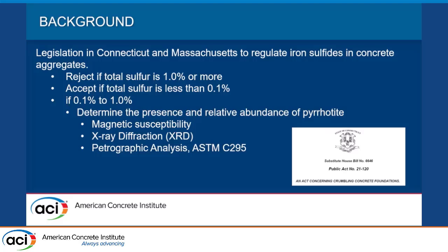So X-ray diffraction is a great tool. It's a wonderful tool to identify the crystalline components in anything, and in this case in concrete or aggregates. The issue with that is that the detection limit is generally identified as 1 to 5%. And again, we're looking at concentrations down to 0.1%. I don't want to say that it can't be done by XRD, but you really need some optimal conditions, specialized equipment, in order to get that identification that low.